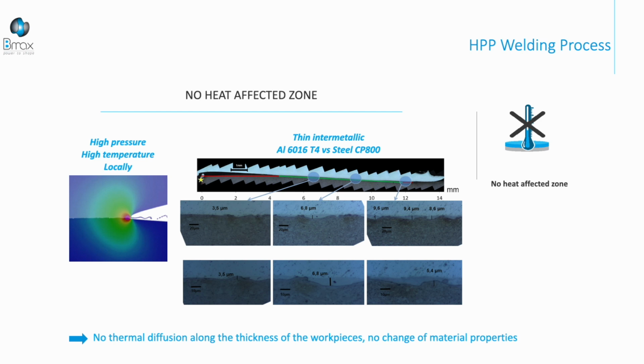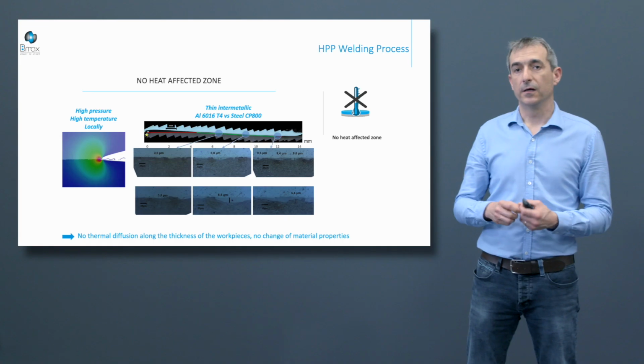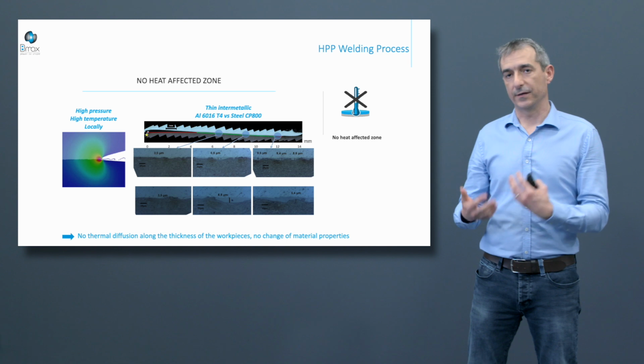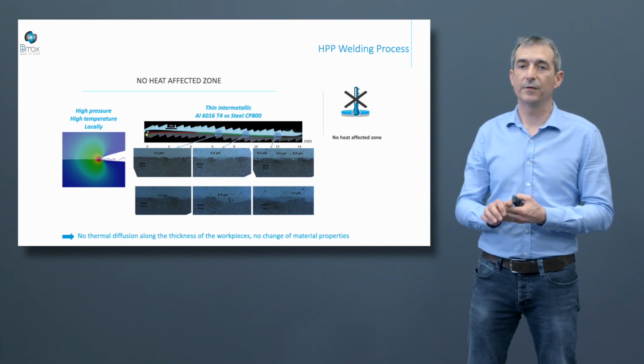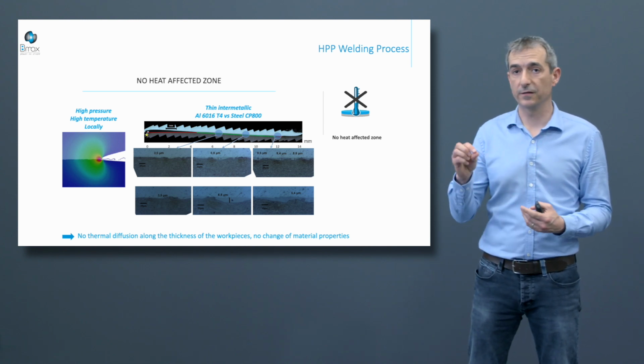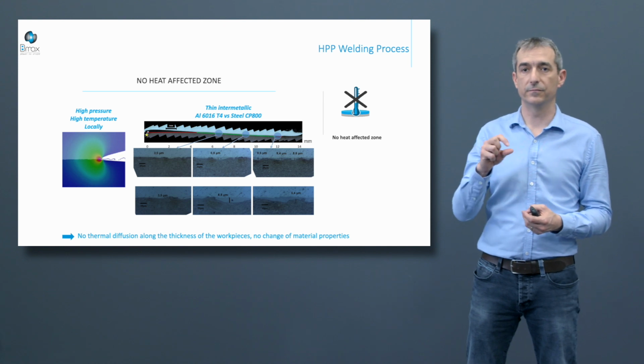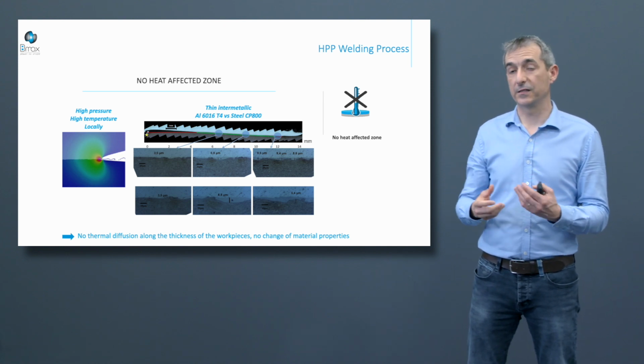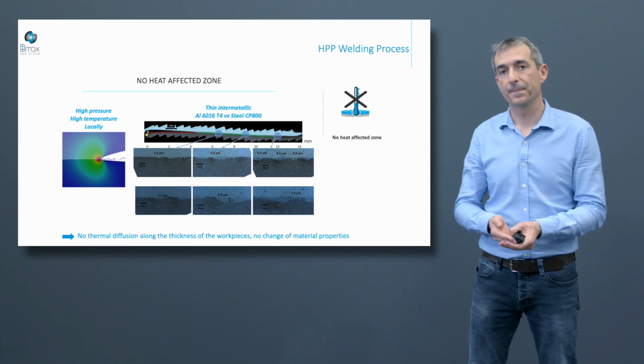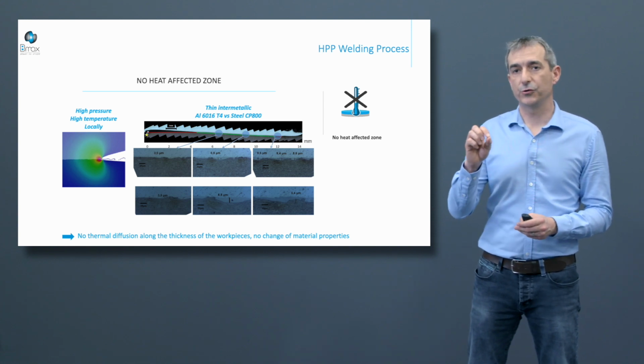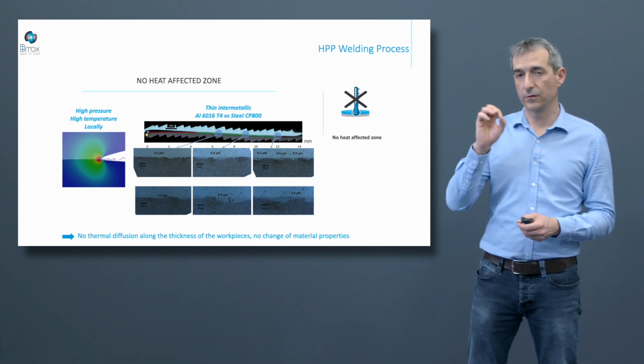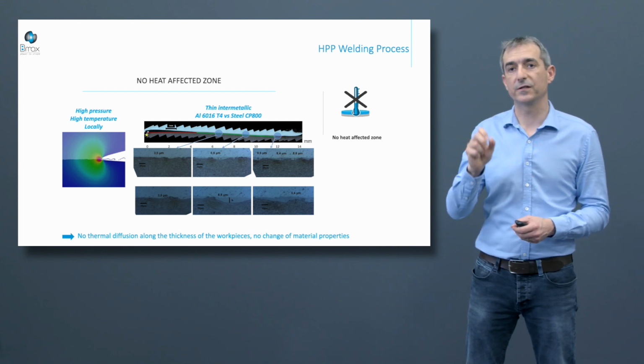By this way, we create very high pressure and high temperature very locally at the contact closing. This high temperature and high pressure generate good intermetallics for dissimilar materials, very thin, a few micrometers in thickness. By this way, we have a strong welding. But the high temperature is very local. It's just a spot and very short in time.